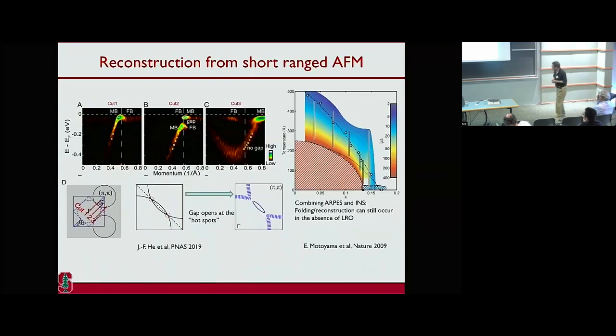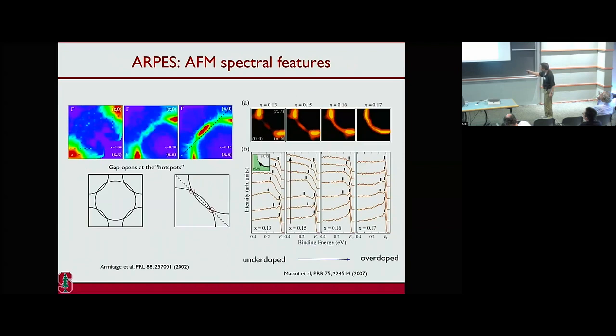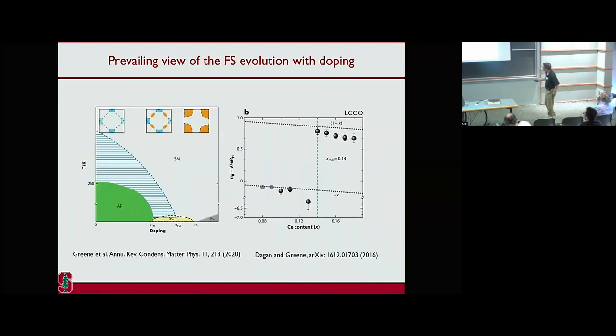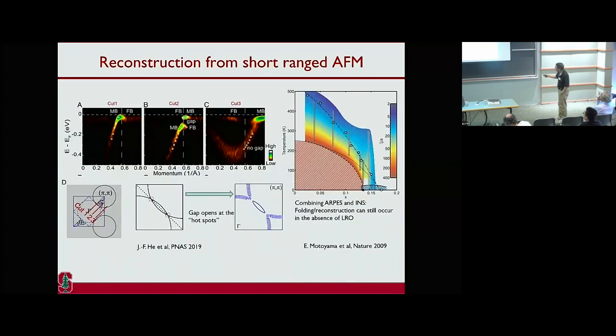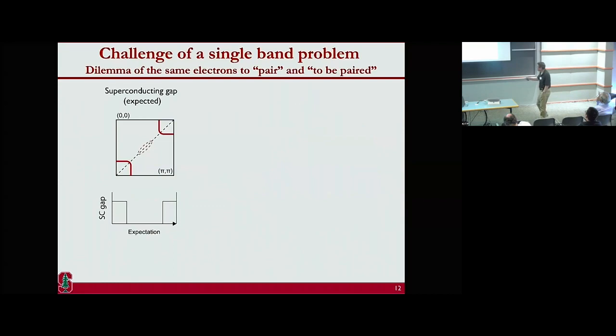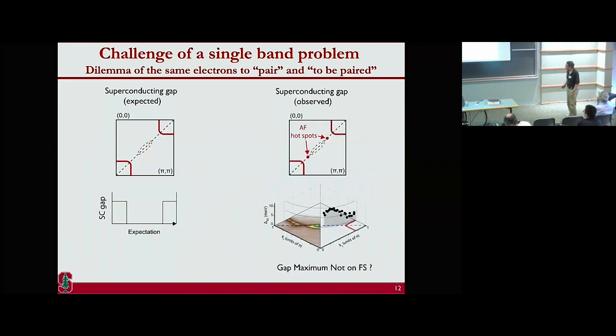Okay, now more recently, we asked this question: can we see basically the other side of the Fermi surface? Usually, you only see one piece, and indeed, in the electron doped system, you begin to see the folded band of that. And this happens in this regime, okay? In this regime where Martin's group has shown that it's sort of 2-dimensional magnetic order, it's commensurate, okay? That's where they go. So now, again, here's the reconstructed Fermi surface. Your expectation will be gap on top of this Fermi surface, okay? Because after all, superconductivity happens at a much lower temperature than what is perceived.